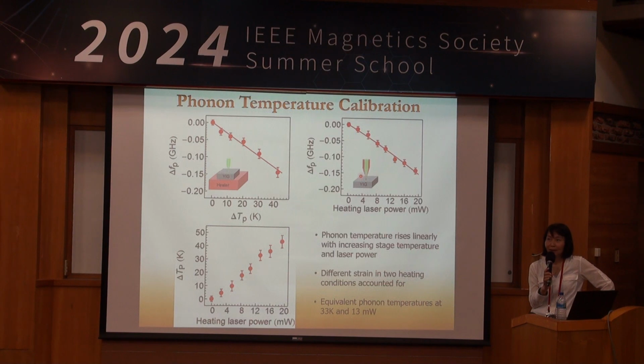And this is counterintuitive. If they're coupled weakly, in a YIG sample that has very low damping, in fact, phonons and magnons couple very weakly, you can drive them out of equilibrium. If they're strongly coupled, they always reach local equilibrium. So the fact that I can drive them out of equilibrium is entirely consistent with phonons and magnons in YIG coupling very weakly. As a result, they can get out of equilibrium.